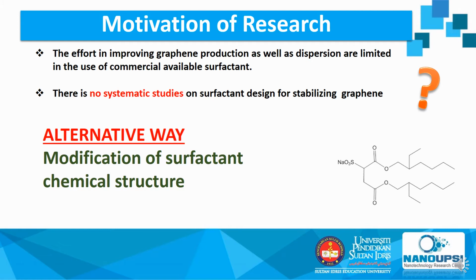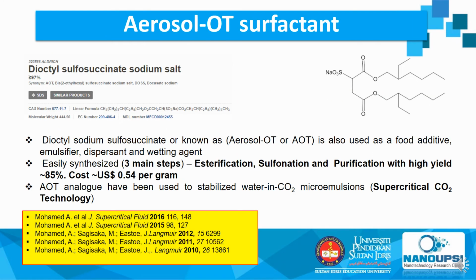Therefore, one of the ways is through modification of the chemical structure of AOT or Aerosol OT. AOT, whose full name is sodium dioctyl sulfosuccinate, is a typical surface active emulsifier, disperser, and wetting agent, and can be easily prepared through 3 main steps with a high yield of up to 85%. This is also part and parcel of our group's experience in preparing surfactants to stabilize water-in-CO2 microemulsion, which has been published in the following papers.